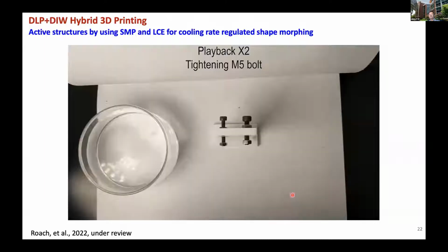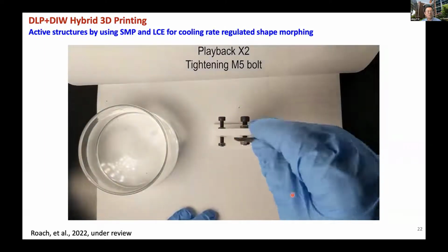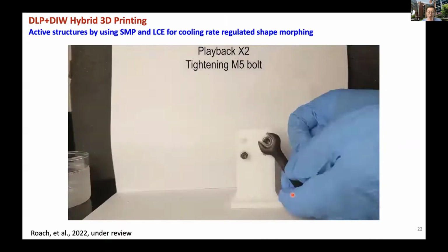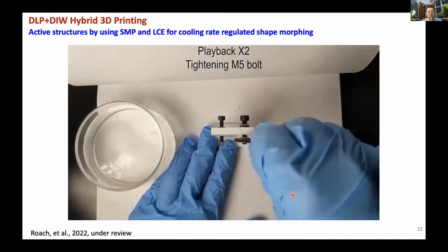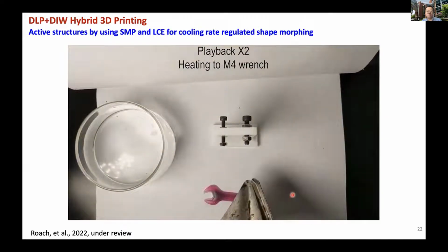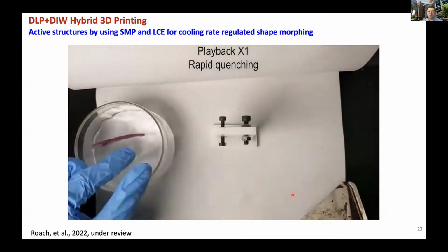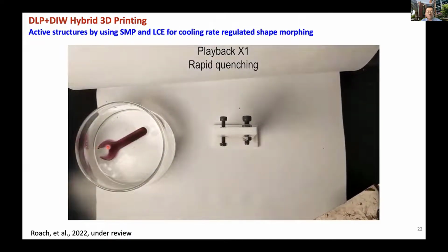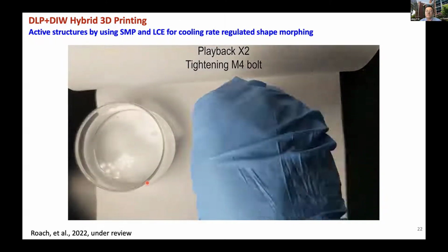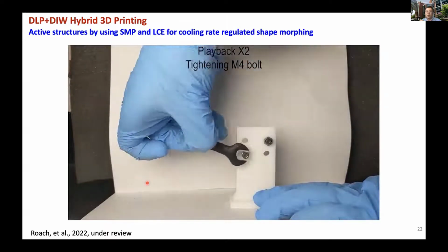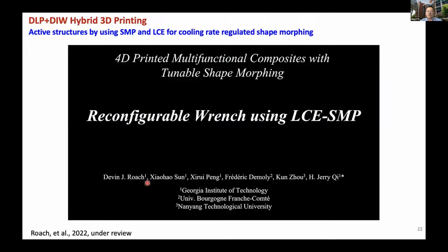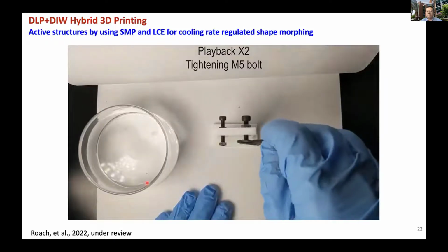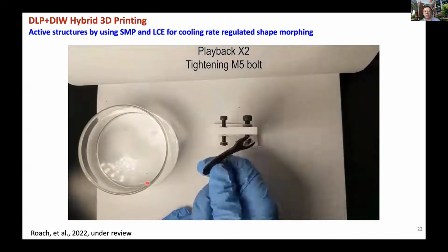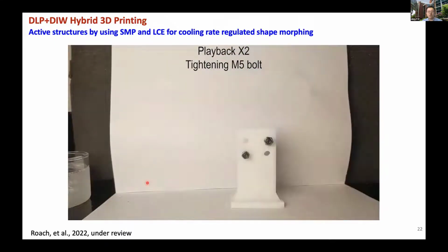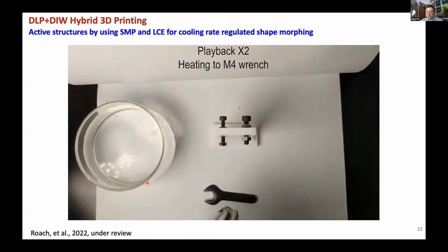Certainly, you can make a gripper for soft robotics, but we're making too many grippers. So Devin came up with a new idea: why don't we make a wrench? In this case, we print a wrench and put the liquid crystal elastomer at this edge, such that with different cooling and heating rates, we can adjust the size of the opening of the wrench. So we can make it fit an M4 bolt or an M5 bolt, depending on how fast I cool it. I can change it into different shapes. We can make an adjustment, so we make a multifunctional wrench in this case.